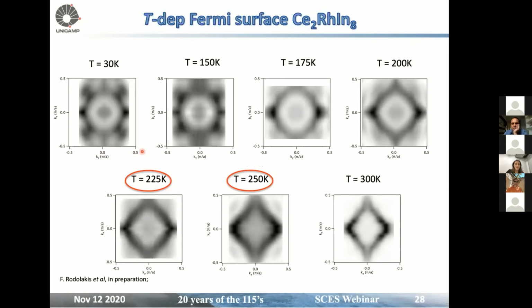But anyway, if we go from low to high temperature here, we see a nice change on those pockets around gamma, around Z point, sorry. And from extensive studies on T-dependent ARPES, we could conclude that the main changes are happening around 200, 250K. So those are big topological changes in the Fermi surface.